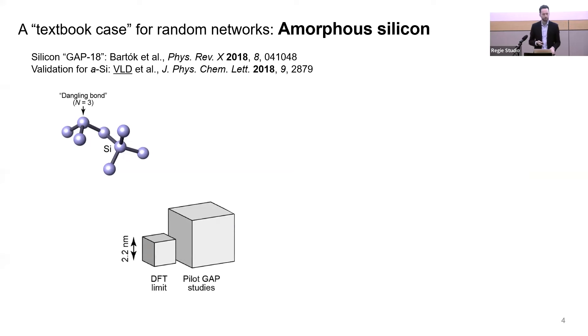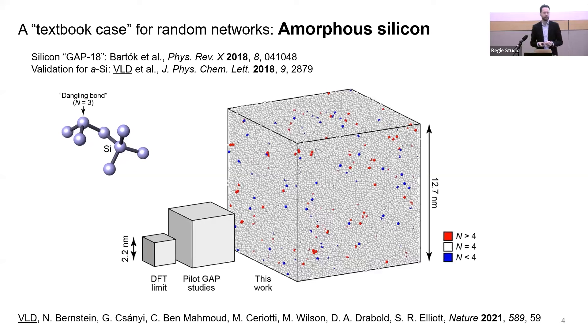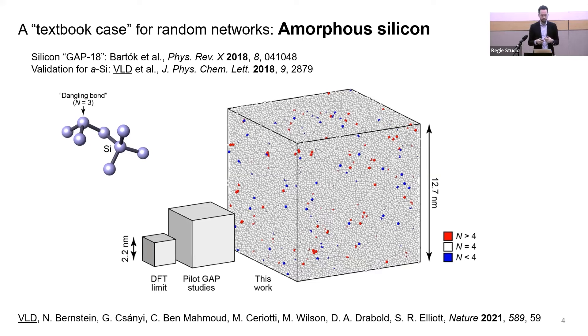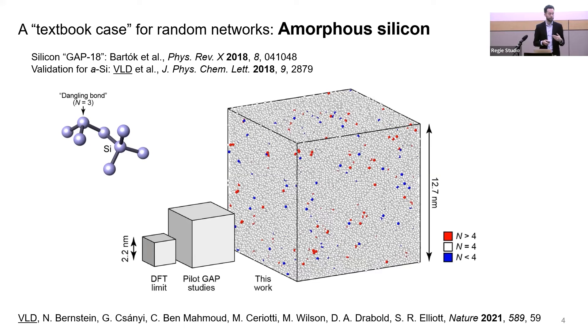What I'm showing you now is 100,000 atoms of amorphous silicon in a simulation box. Most of the atoms are fourfold connected and have no color, but there are a few coordination defects in red or blue, which are really important to get right. This system was simulated using a machine learning force field at near quantum mechanical accuracy.